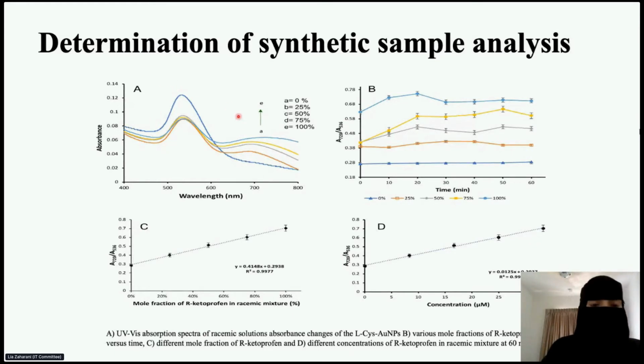by mixing different percentages of R and S ketoprofen. In this spectra, we have tried different percentages of R and S ketoprofen. A, with 0% R ketoprofen, shows the nice peak here, but there is no peak at 720. Then we increase the percentage of R ketoprofen. B is 25% R ketoprofen and 75% S. C is 50-50 of both, D is 75% R ketoprofen, and E is 100% R ketoprofen.